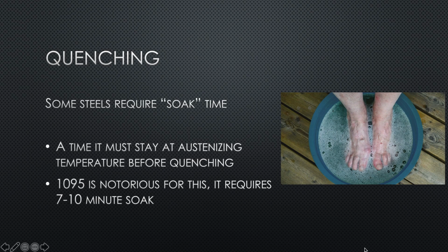Soak time. This is another thing that you will have a problem with in a forge for things like 1095 that require a soak time. It's really hard in a forge to maintain a temperature for a certain amount of time. You really have to fiddle with your forge to get it just right so that you can have the steel stay at a temperature, because usually it's going to try to keep heating up your steel. Obviously, this is trivial in an oven.